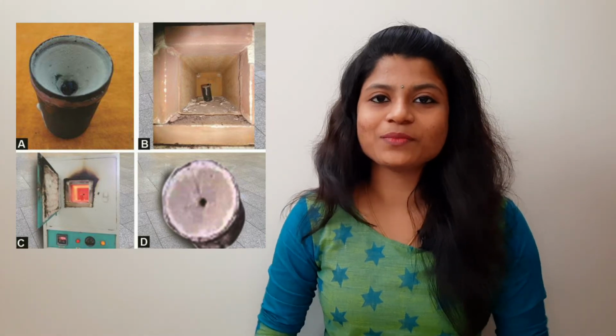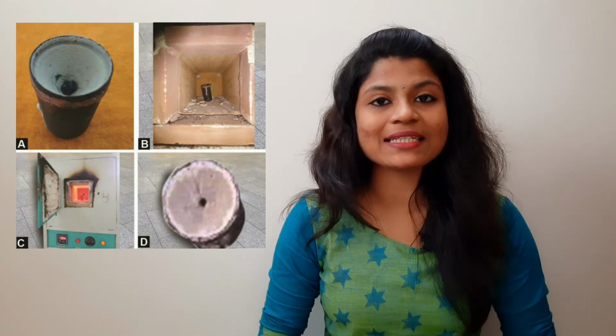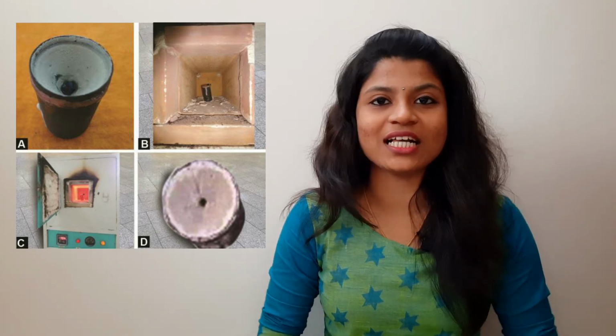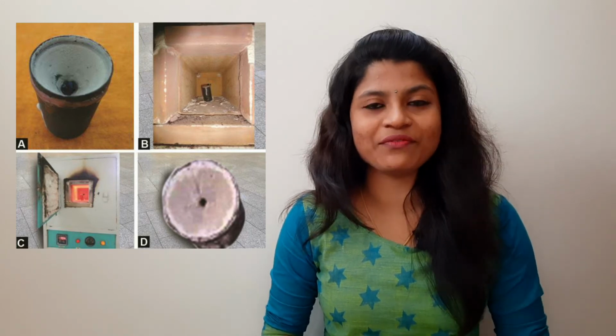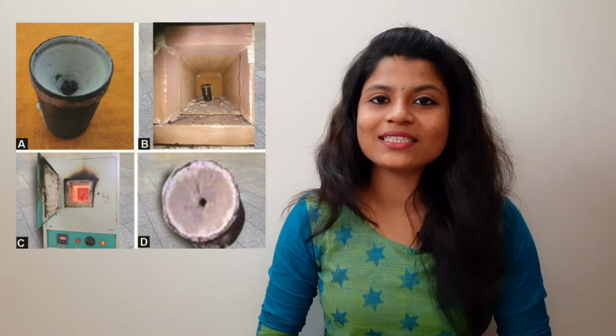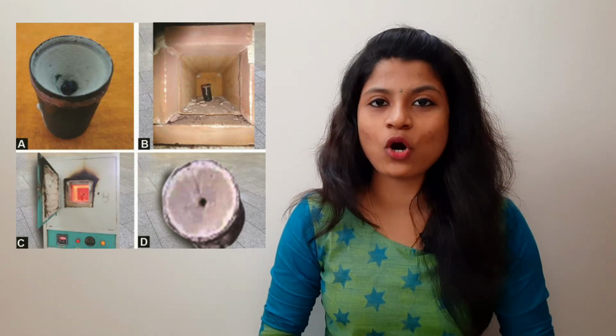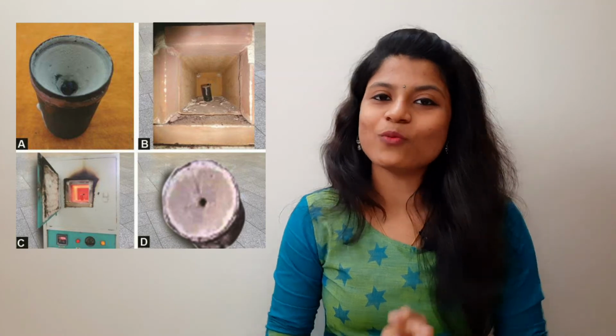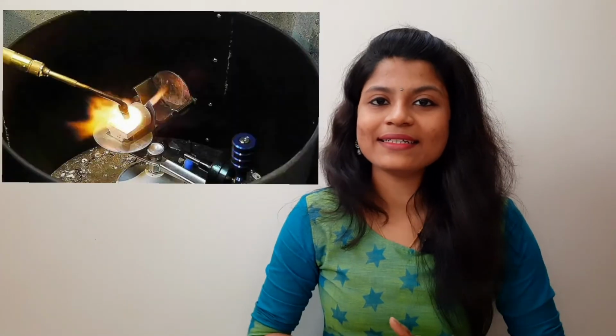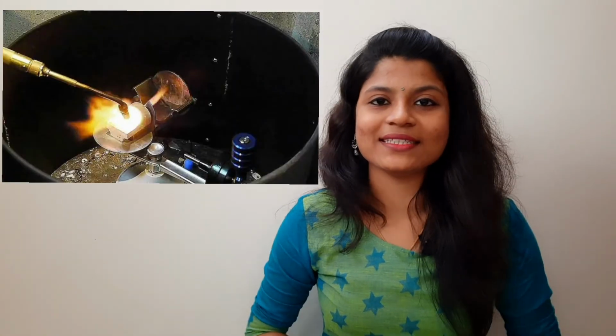If it is gypsum bonded investment, it is heated to a maximum of 500 degrees Celsius, and if it is phosphate bonded investment material, it is heated up to a maximum of 700 degrees Celsius. After burnout, we get the mold and it is time for casting.